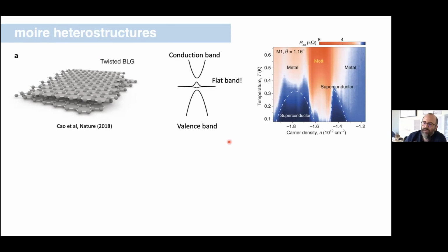So that is also rather unique amongst materials that host these properties otherwise. In more conventional heavy fermion systems or cuprate systems, etc., generally you vary the number of free carriers by switching out atoms. You substitutionally dope the system. In this case, you don't have to modify the lattice at all. You simply add or remove electrons through a gating technique. Okay, so that gives a really great degree of control and tunability of these systems that generated a lot of excitement right away when this was reported a couple of years ago.